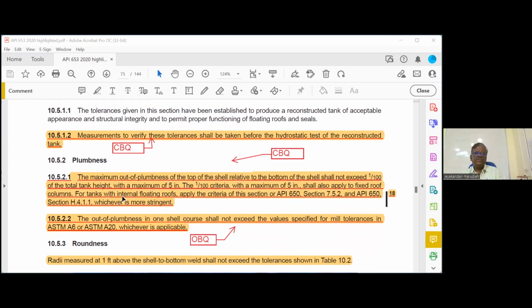So plumbness, highlight this one. The maximum out of plumbness of the top of the shell relative to the bottom shall not exceed 1 by 100 with a maximum of 5 inch. The 1 by 100 criteria with the maximum shall also apply to fixed roof columns and for tanks with internal floating roofs.